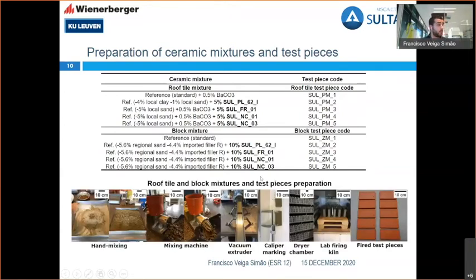With that, we do the normal procedures, from the hand mixing to the mixing machine to the vacuum extrusion of these roof tile and block test pieces, caliper marking for drying and firing shrinkage, drying in an industrial chamber, and firing in the lab in an electric kiln. At different temperatures, we fire the roof tile mixtures at an average of 985 degrees Celsius and the block mixtures at a lower 965 degrees Celsius. With that, we have the fired test pieces.